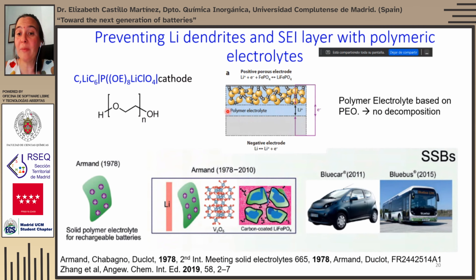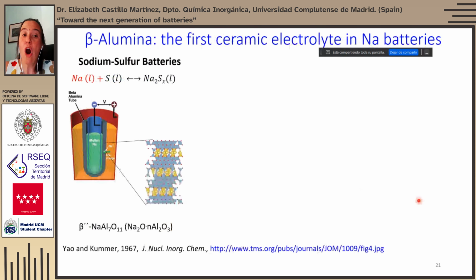The good thing of this polymer electrolyte is that there is no decomposition, so no SEI layer formation. Actually, these polymeric batteries, together with lithium iron phosphate, have gone into commercial batteries, and are used in the Blue Car that has been running in Paris since 2011, as well as in the Blue Bus that has been running in Paris since 2015.